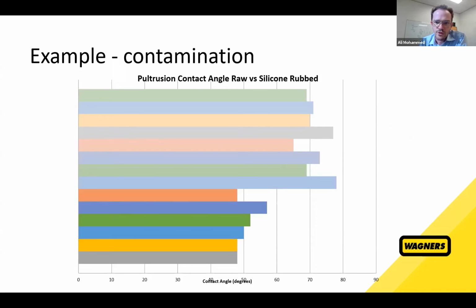Here's a bit of a real world example where we've used this contact angle device to check for silicone contamination. We've purposely rubbed a piece of pultrusion with silicone, and we've measured the contact angle of that surface before and after the silicone's been rubbed on the surface. You can see the bottom half is just the untreated pultrusion, so it hasn't been rubbed with silicone, sitting around the high 40s, 50-degree contact angle. And the top half is the surface after it's been rubbed with silicone. So you can see how this device and this unit of contact angle can be used to assess a surface and assess the contamination on the surface, or assess the surface energy of a surface, so to speak.